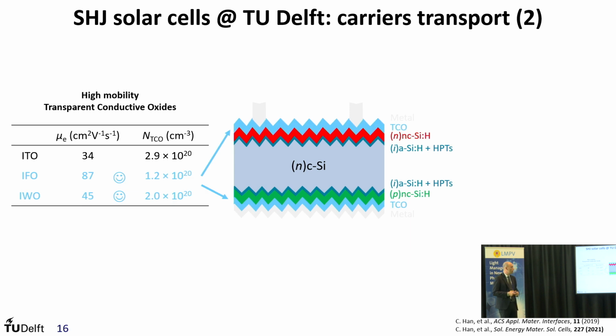Then we pass on to transparent conductive oxides, that are a crucial type of materials that are also extremely needed for this type of architecture. I'm sure that Monica later will deep dive much more into TCOs, of course. In our case, we developed a number of indium-based TCOs, like fluorinated or tungsten-doped indium oxide, with much better performance with respect to the standard ITO in terms of transparency and also conductivity. Of course, we are very well aware that indium is a critical raw material, is not sustainable in the long run, so we are of course also looking into indium-free or indium-less approaches in the near future.